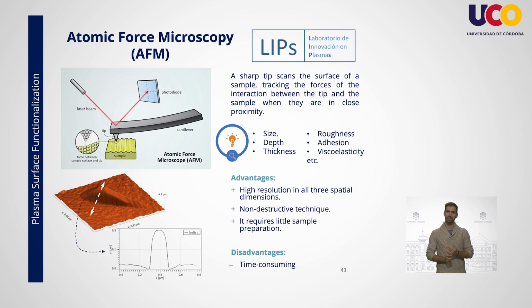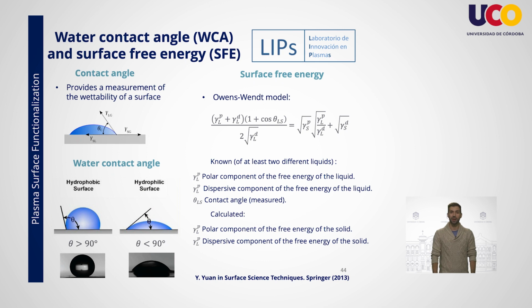Among its advantages is that it is a non-destructive technique that can achieve high spatial resolution. It also requires minimal sample preparation, but on the other hand, the analysis of large areas may require long times, limiting its application. Finally, another very common type of measurement is contact angle and free energy. The contact angle is defined as the angle made by the intersection of the liquid-solid interface and the liquid-air interface. A high contact angle indicates a low chemical affinity or a low degree of wetting.